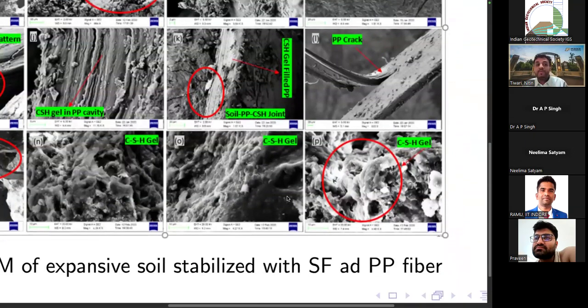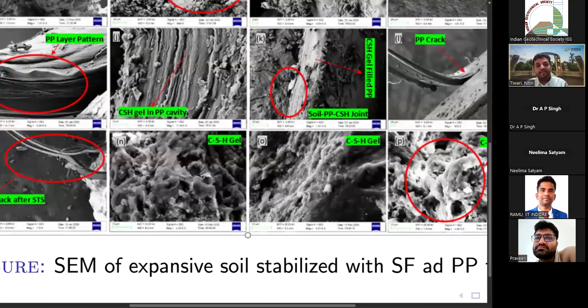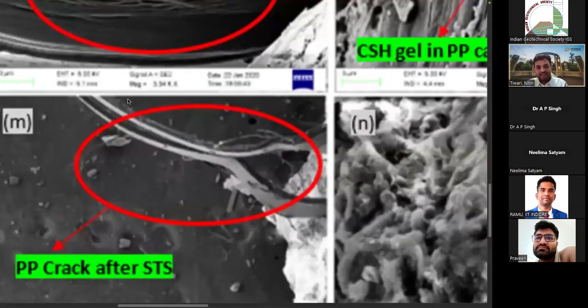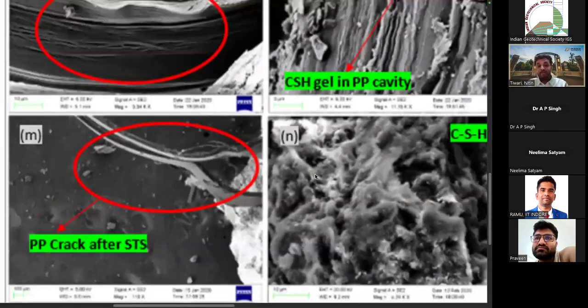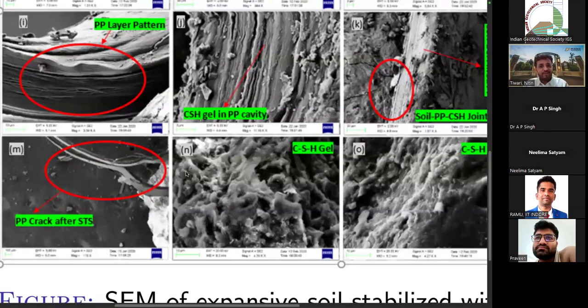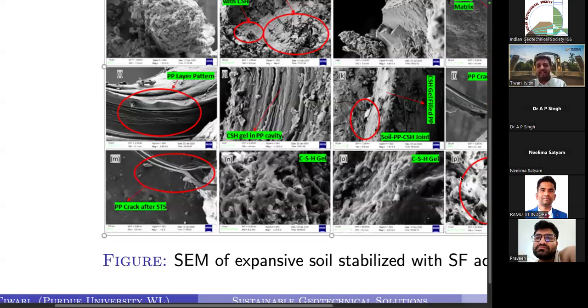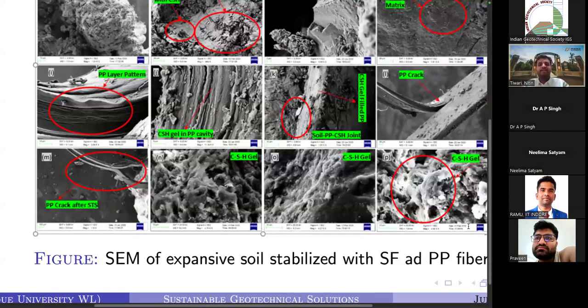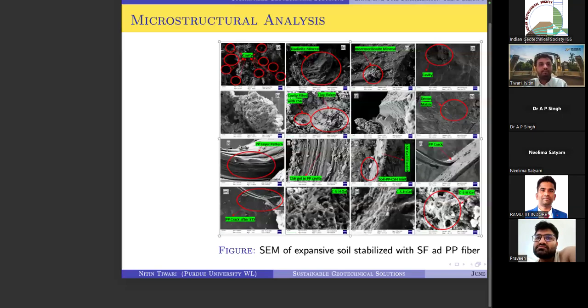So we really observe that, and you can see even without treatment, the fiber condition is really bad. So with treatment, we are getting strong fiber bonds. And at the same time, you can see a lot of CSH gel is flowing. You can see a very good CSH formation inside these soil samples.